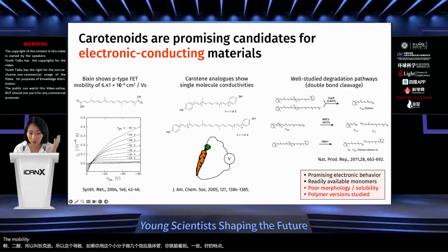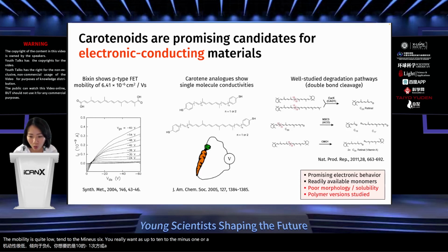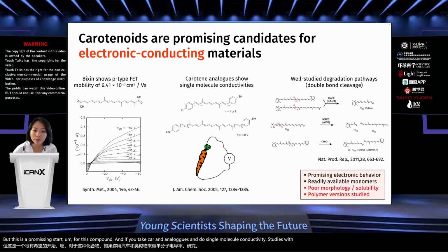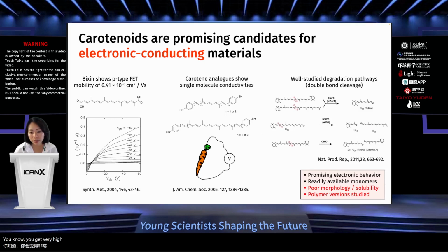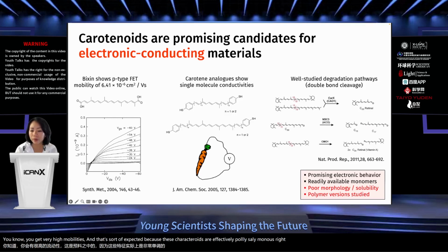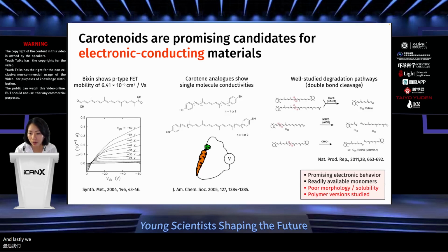The mobility is quite low, it's 10 to the minus 6. We really want this up to 10 to the minus 1 or 0.1, even 1, right? But this is a promising start for this compound. And if you take carotene analogs and do single molecule conductivity studies with AFM, you get very high mobilities. And that's expected because these carotenoids are effectively polyacetylene monomers, right? And lastly, we really like carotenoids because they have really interesting degradation pathways that are known.